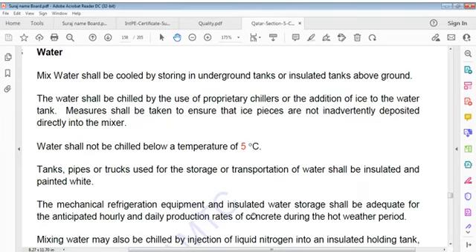Water shall be chilled by use of proprietary chillers or addition of ice to water tank. Measures shall be taken to ensure that ice pieces are not inadvertently deposited directly into mixer. Water shall not be chilled below a temperature of 5 degrees Celsius.